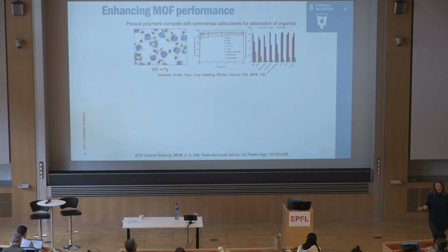What I noted is that this material in blue really outperforms the one in green that's commercially available. And I began to ask myself why, because as a chemist, we know kind of the structure dictates the function of materials. And so I began to look at these materials, and what I realized is that theirs is just more porous, okay? The surface area is around 260 meters squared per gram in what they made, versus the commercial material is around 10 meters squared per gram. So this kind of struck my curiosity.